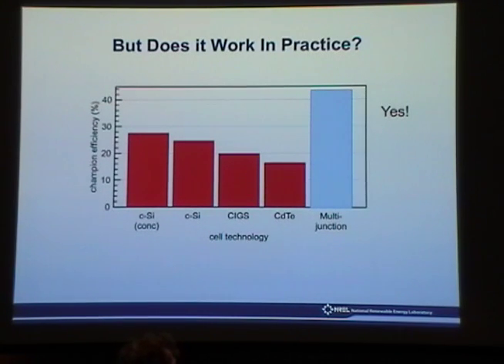Crystalline silicon under concentration, crystalline silicon at 1 sun, CIGS, cadmium telluride. I assume over the next week you'll hear about some of these technologies. I didn't include organic photovoltaics on this. Here's multijunction cells. 42%, 43%. The world record is 43.5%. So that's about 15 percentage points higher than the next bar on the chart. So it does work. You can get much higher efficiencies when you stack the cells into a multijunction.